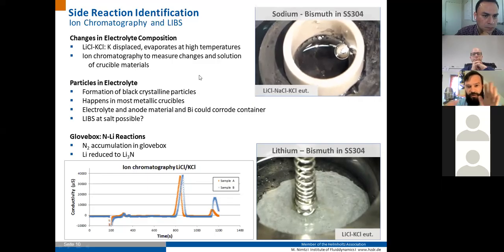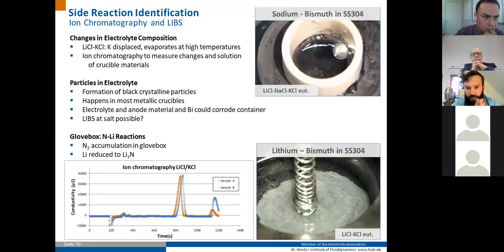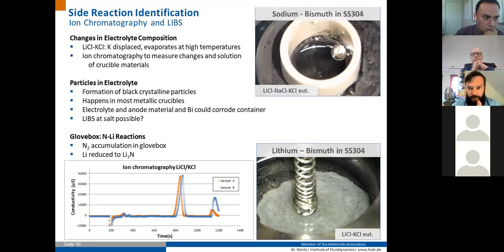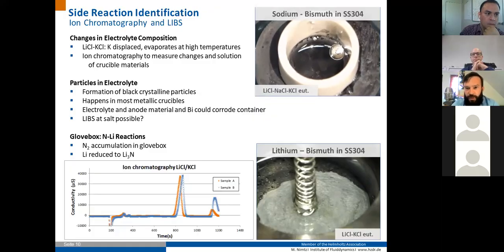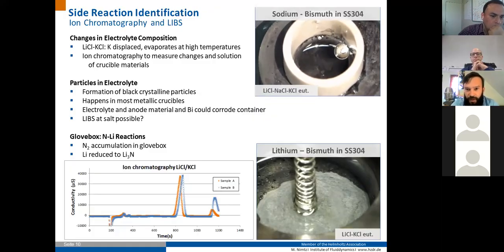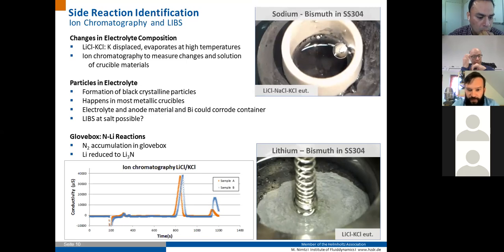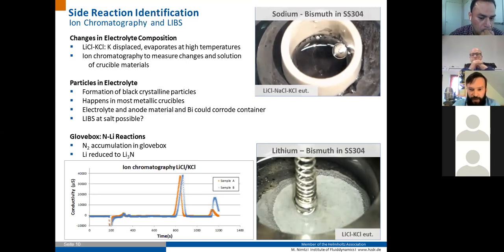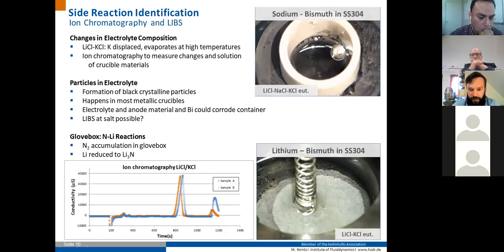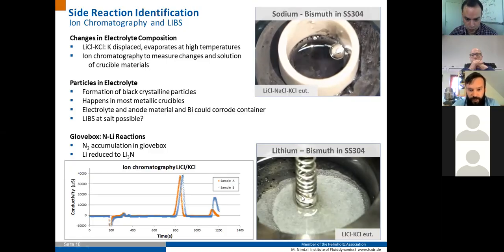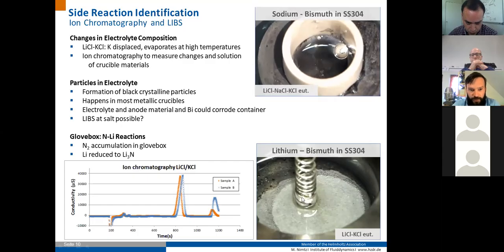If you change the electrolyte composition from the eutectic point, this will have the effect that the melting temperature of your mixture will be higher, which means you need to operate the cell at higher temperatures, and you can have problems with crystallization of the electrolyte if you do not maintain this higher temperature.